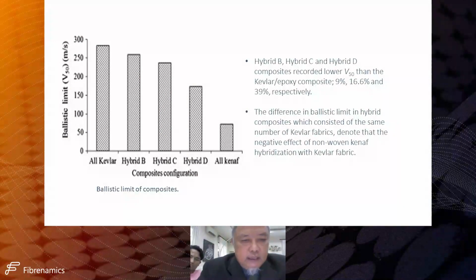And this is some of the result that we get in terms of ballistic limit, and also the result as we compare the materials, all Kevlar up to all Kenaf. So we can see all Kenaf has got the lowest value. Hybrid B, C, and D recorded lower than Kevlar epoxy composite by 9, 16, and 39 percent respectively. The difference in ballistic limit in hybrid composites, which consisted of the same number of Kevlar fiber, denotes the negative effect of non-woven Kenaf hybridization with the Kevlar fabric. So we can see that with Kenaf the value is reduced.